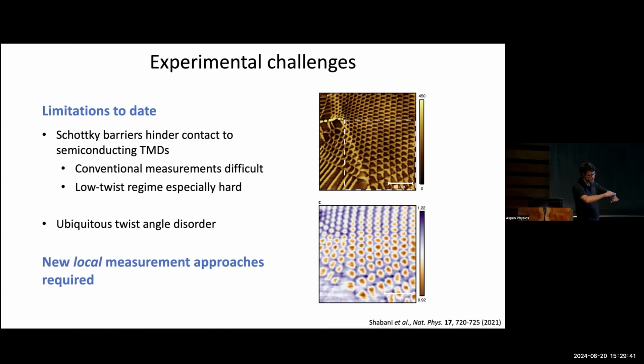And so you can pick something up, twist to a target angle, put it back down, but what you get out may or may not be exactly what you wanted. And in fact, if you look even on scales of hundreds of nanometers, this is just one particular example from a scanning tunneling microscope measurement that can resolve this. You can see that the periodicity, the Moiré wavelength, is changing quite a bit. And that obviously is detrimental if you want to do some sort of large global transport measurement, for example, even if you can get the contacts.